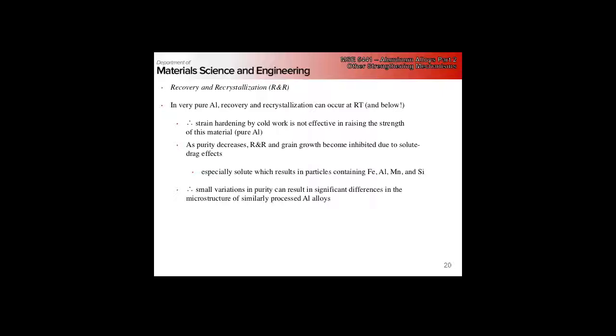right? But notice this is a problem with the things we can't remove: iron, manganese, and silicon, right? Those are the ones that tend to form these insoluble particles and stuff we can't get out of our alloy by processing. And so this is the big take-home message here, right? Very small variations in the purity can result in very significant differences in the microstructure and the property and the ultimate performance of aluminum alloys, even ones that go through the same processing steps.